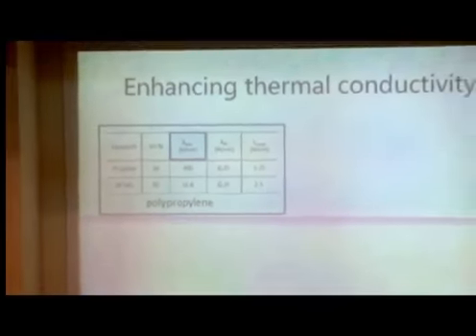Huge difference in thermal conductivity, 400 for copper and about 10 for talcum powder. But then when we measure the resulting thermal conductivity, we see that the talcum powder composite wins. The resulting thermal conductivity is twice the one of the copper composite, which makes you wonder, maybe.